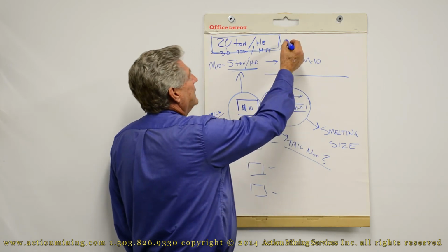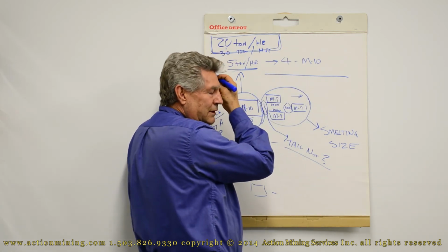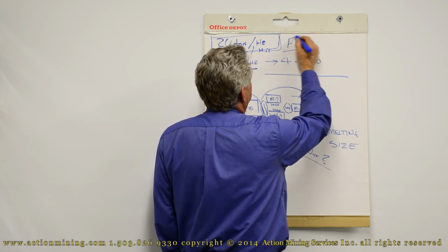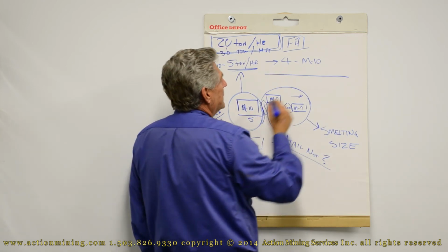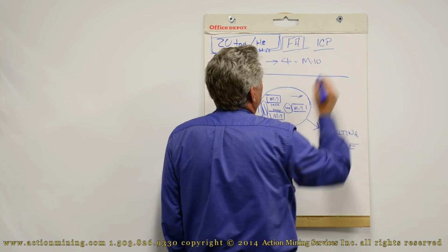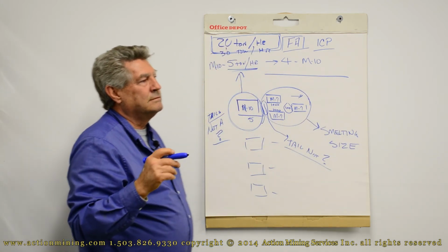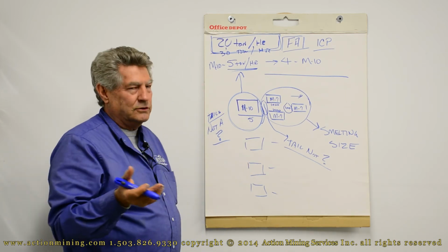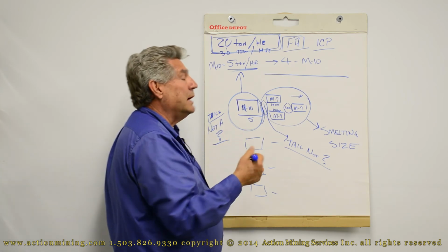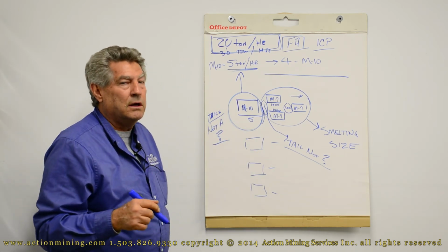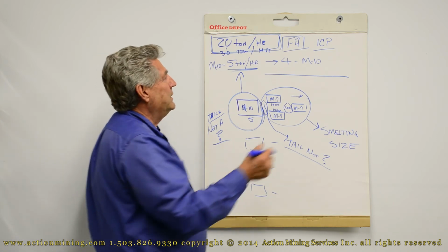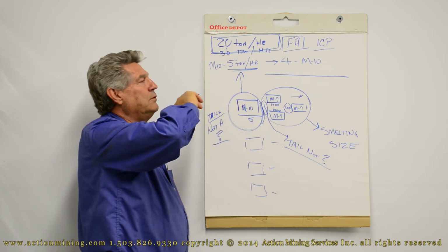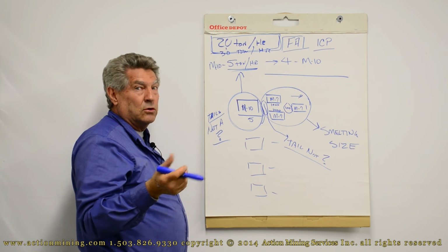If you come up here and you assay this, and I say fire, I trust fire assays if done properly. ICPs have a wish factor. And see now, wish factors in mining usually cost you lots of money. I don't like ICPs. ICPs are very good for telling you what else is in there and what the possibilities are. But they won't tell you if this gold is a gold chloride, because it's probably gone when they do that. Or they may be getting all the gold chloride.